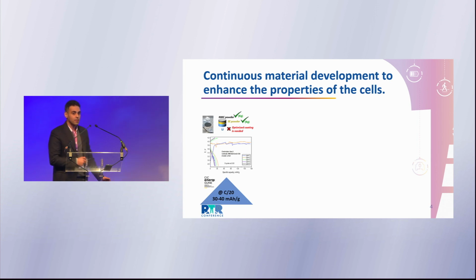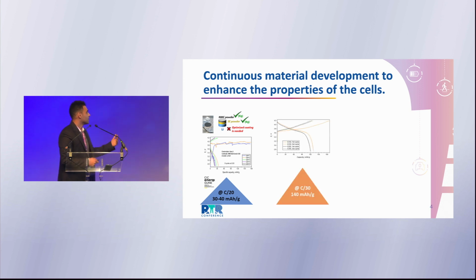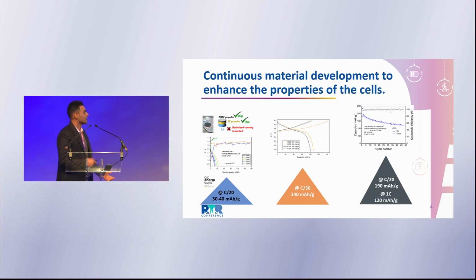And this is just an example of how, by tuning our materials, we can improve the performance of the cell. For example, on a coin cell level, this is the performance we had at the very first of the project, in the first year. So we could only get 30 to 40 milliampere hour per gram capacity. Then we optimized the material, the capacity improved, and at the last year, at the coin cell level, we could reach 190 milliampere hour per gram at C/20. And at 1C, we could get 120 milliampere hour per gram.